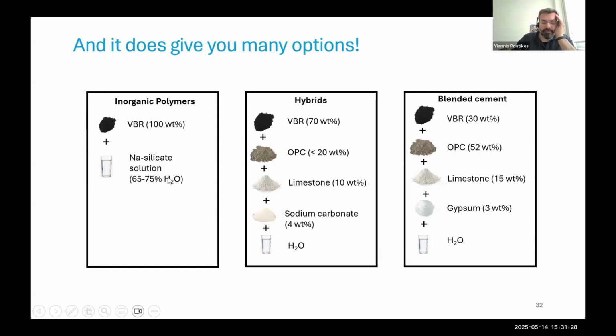Here are again the different terms, but now you see the additions. In the first case, you add a sodium silicate solution or potassium silicate, doesn't matter. Sodium and potassium are both possible. In the second case, you have a very low amount of alkalis. Also, interestingly, these are solids, sodium carbonate, and you just add water. Careful, in the first case this is usually a solution. In this case, it's just solids and addition of water. So this is like business as usual from a processing side.